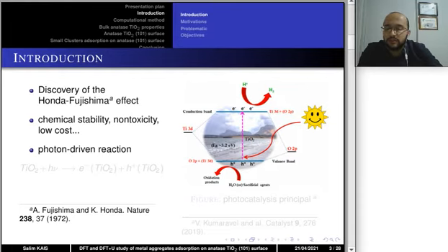When a photocatalyst is exposed to light of the desired wavelength, the energy of the photon is absorbed by an electron of the valence band and it is excited to the conduction band. In this process, a hole is created in the valence band. This process leads to the formation of a photo-excited state, and electron-hole pairs are generated. This excited electron is used for reducing an acceptor, while the hole is used for oxidation of donor molecules. The generation of the electron-hole pair can be written as follows.